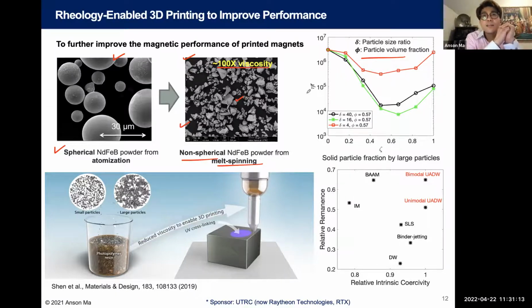We got inspiration from the late 60s and early 70s, and we played this game of particle size distribution. By doing that, we identified a certain particle size ratio and particle volume fraction, based on the large to small particle ratio, where we find a spot that gives us the lowest viscosity. Then we prepared that suspension and used the same UV assisted printing. And we managed to push out from the previous case to a higher performance in this direction.